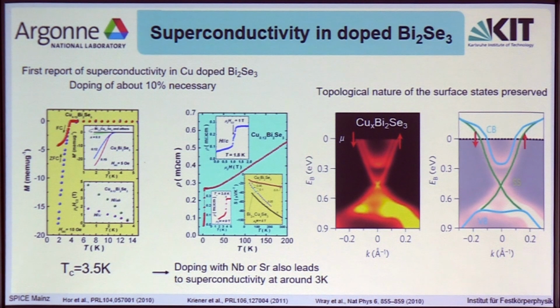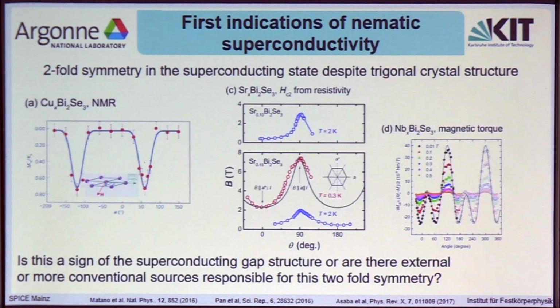Now, also very shortly afterwards came the first measurements that showed a very peculiar feature of these systems, namely that if you look at the in-plane anisotropy, despite the trigonal crystal structure, we actually see a clear twofold anisotropy in the plane. This has been seen in various different measurements, namely in copper-doped bismuth selenide and the NMR Knight shift. We can see it in resistivity measurements for strontium-doped bismuth selenide or in magnetic torque measurements for niobium-doped bismuth selenide.